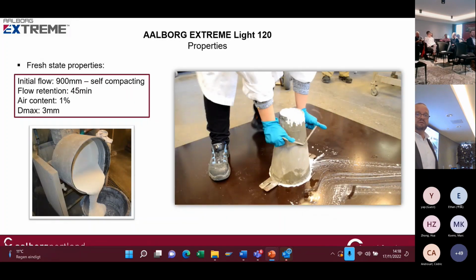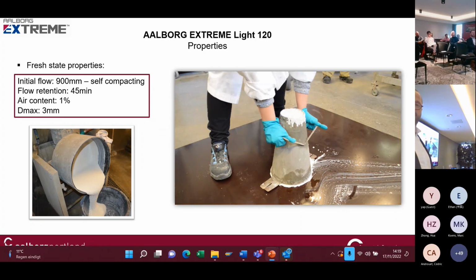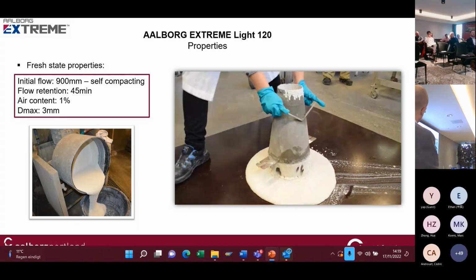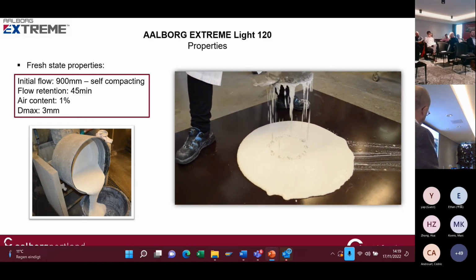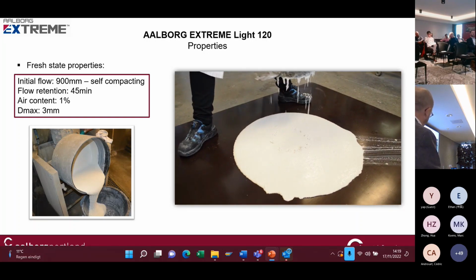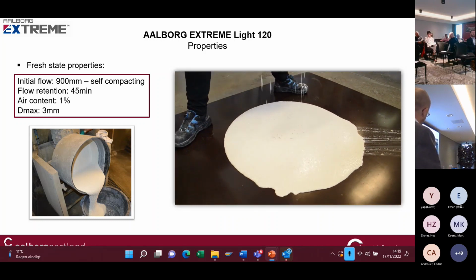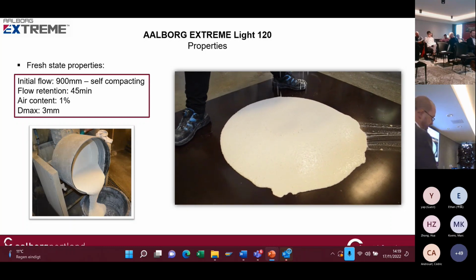So in fresh state, we can guarantee a flow of 900 millimeters, and also a flow retention of 45 minutes. It's in normal conditions, with normal temperatures between 15 and 25 degrees. Of course, if you go higher in temperature, the flow retention will be less. And also going lower is not so good for the flow. And also a very limited air content. And in Aalborg Extreme, we are working with an aggregate of maximum 3 millimeters. Here you can see how it looks like with the Abrams cone. So very slowly flow, but achieving 900 millimeters.